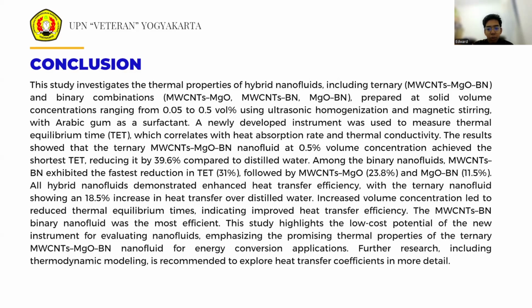This study emphasized the concept of nanoenergy in the context of nanofluid heat transfer. Nanoenergy refers to the heat energy transferred by nanofluids that exhibit superior thermal conductivity due to the presence of nanoparticles. The ternary hybrid nanofluid, particularly the MWCNTs, magnesium oxide, and boron mixture, not only reaches thermal equilibrium faster but also transports 18.5% more heat than distilled water, demonstrating the significant potential of nanofluids for improving heat transfer. This increased heat transfer capability is especially valuable for applications like energy storage, thermal management, and heat exchangers, where maximizing energy efficiency is a crucial part.